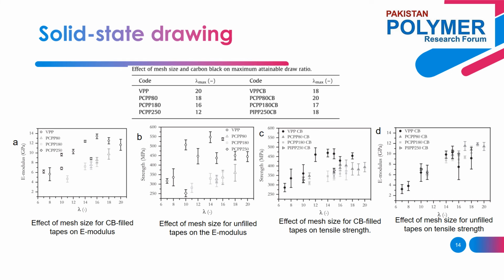Looking at the material without carbon black in the table, it can be observed that the maximum attainable draw ratio decreases with decreasing mesh size for recycled isotactic polypropylene. It is clear that the presence of solid particles which act as stress concentrators is the limiting factor in this experiment. A fine mesh contributes to more stable process operation and high draw ratio.